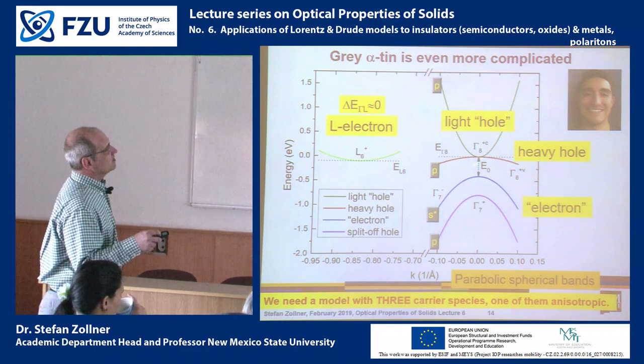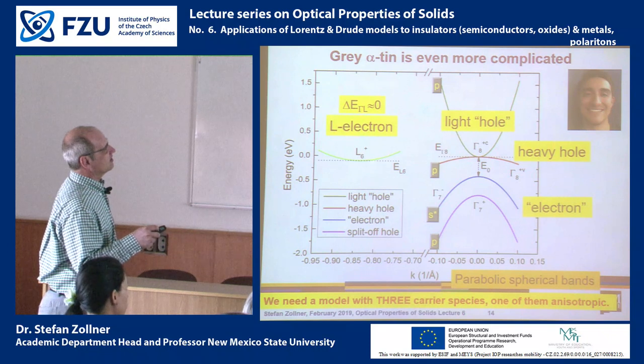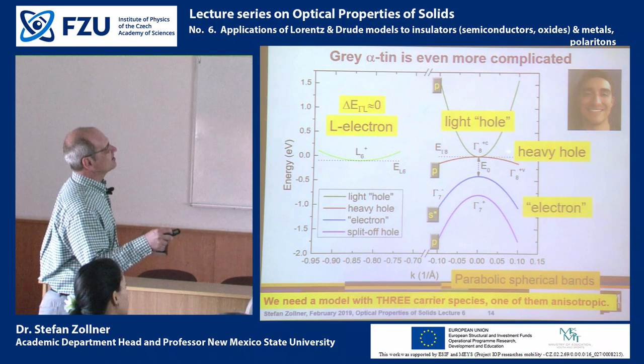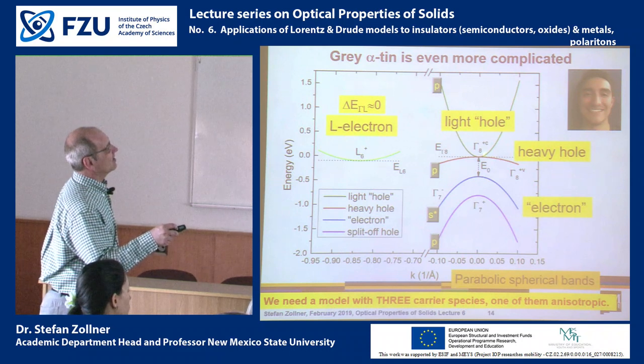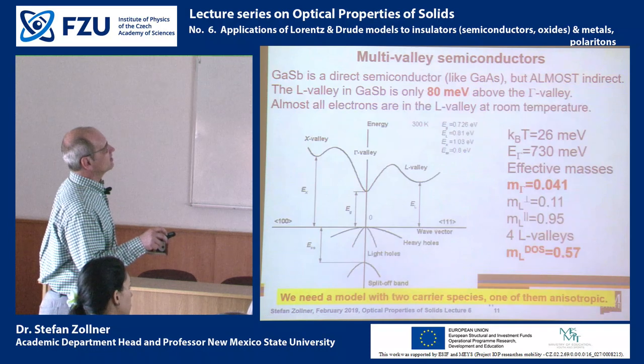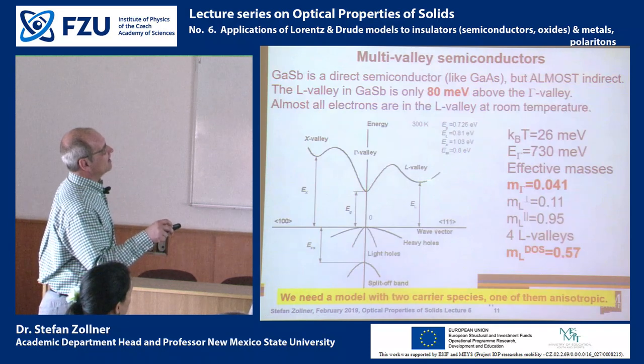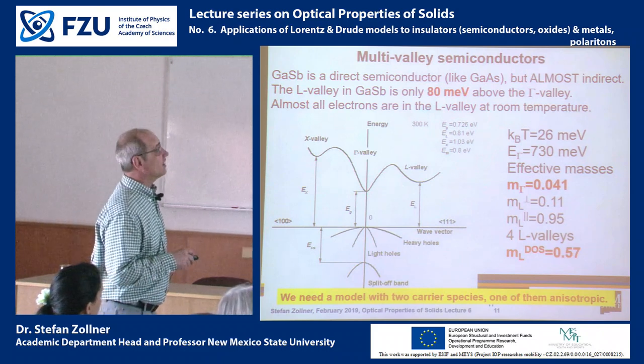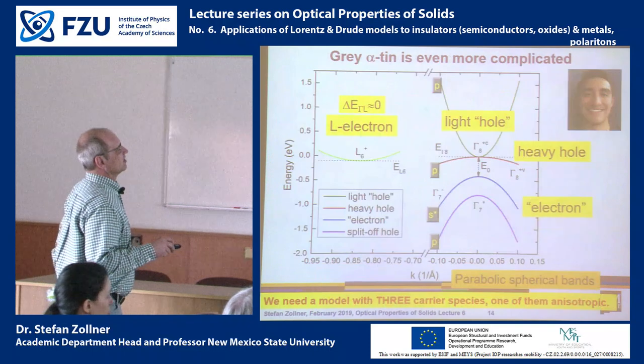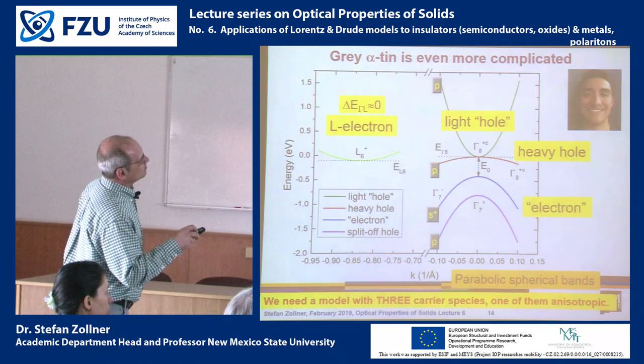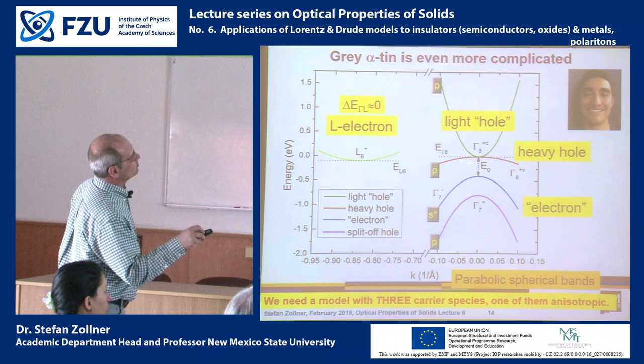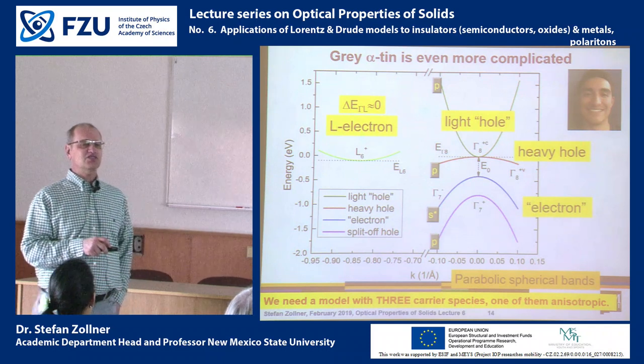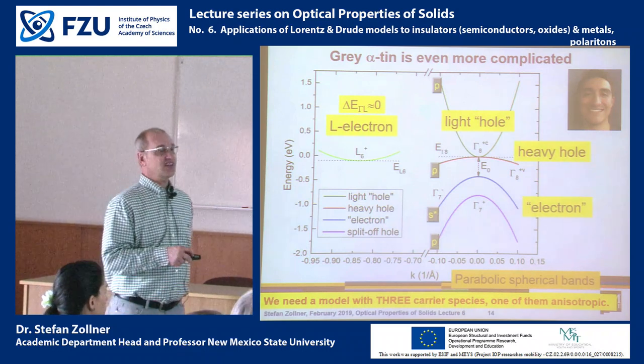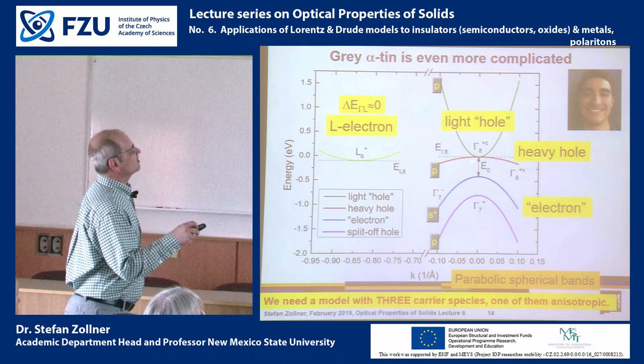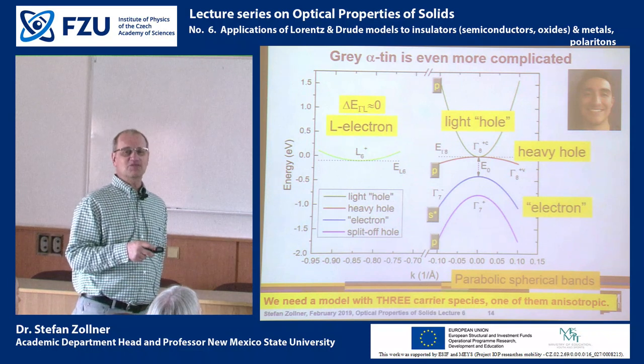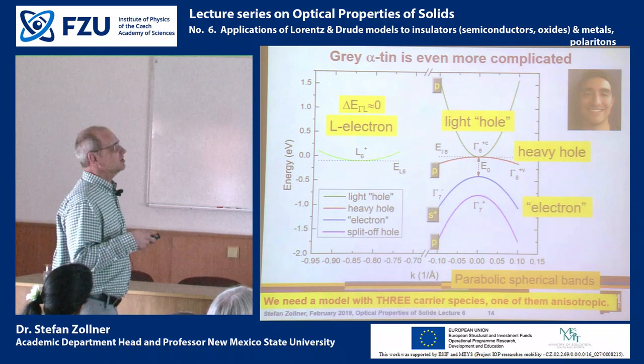And in tin, if we look at tin, then the L valley is at approximately the same energy as the gamma valley. Remember, gallium antimonide, the separation between L and gamma was on the order of 80 millielectron volts. In tin, there's only one paper which tries to quantify this difference, and they say that this difference is about 5 millielectron volts. So in this case, L is almost degenerate with gamma, and now it would be even more interesting to do that temperature-dependent experiment.